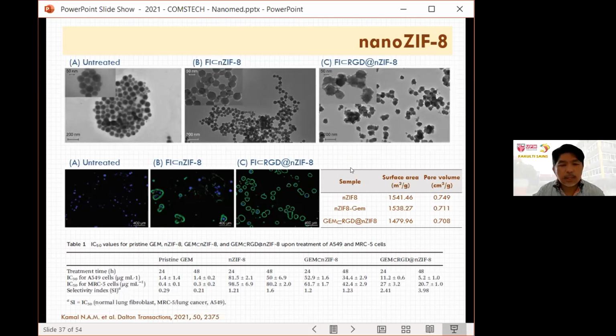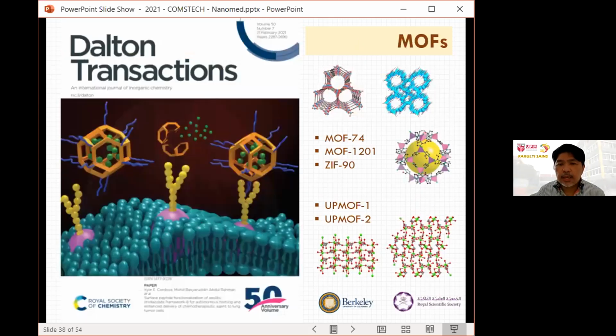From here as well, the data also show that the system that we introduced with the gemcitabine experiences not only efficient uptake within the A549 cells, but also induces obvious cytotoxicity, about 75% at a concentration of 10 microgram, and then apoptosis of about 62% after 48 hours of treatment when compared to the nanoparticle. And we are so glad as well that this paper has been selected as the cover page for the recent Dalton Transactions. For me, it is kind of a beautiful gift to give to my university, which is also celebrating 50 years of UPM, and Dalton Transactions also has its 50 years anniversary volume.